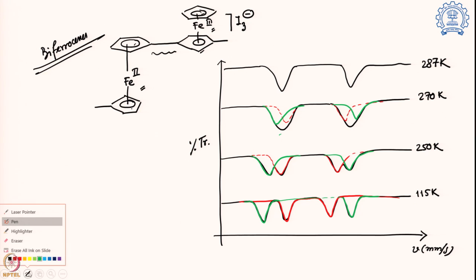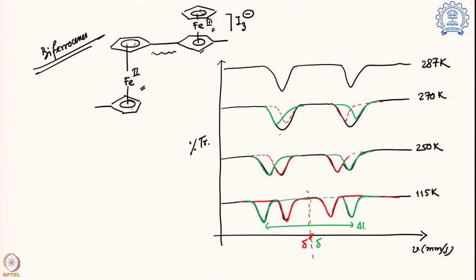So what are this green and the red signal? What I found is that the green and red signals, very interestingly, have pretty similar delta values. But what is different is the delta EQ value. Green is much more separated, whereas the red one is much more shrunk.